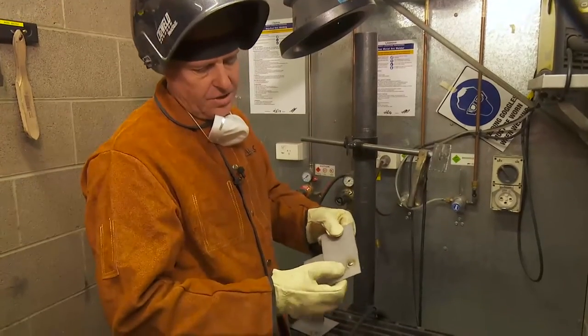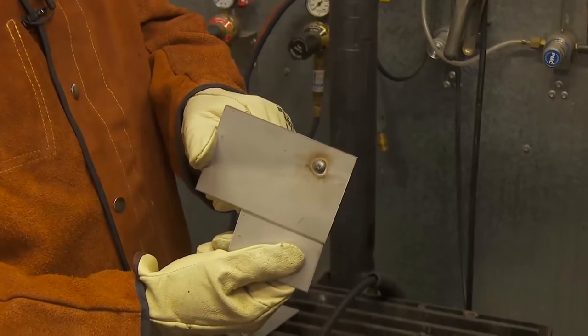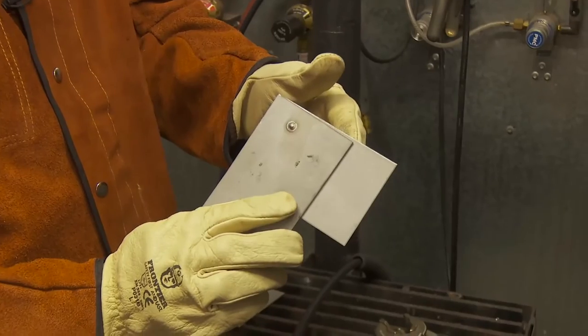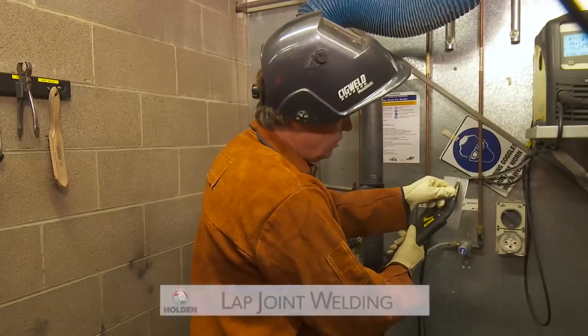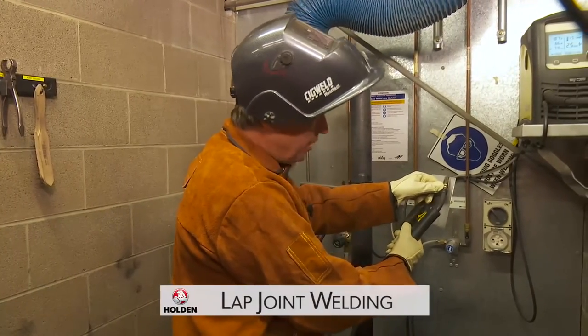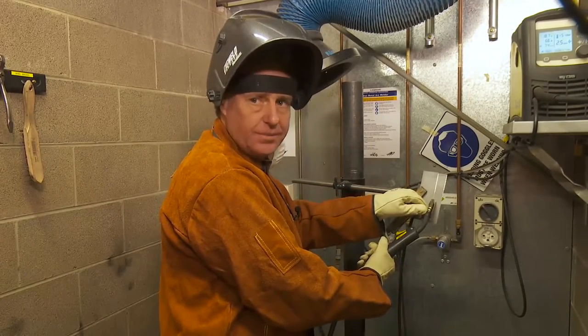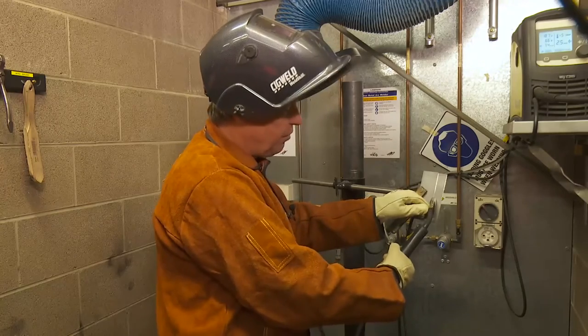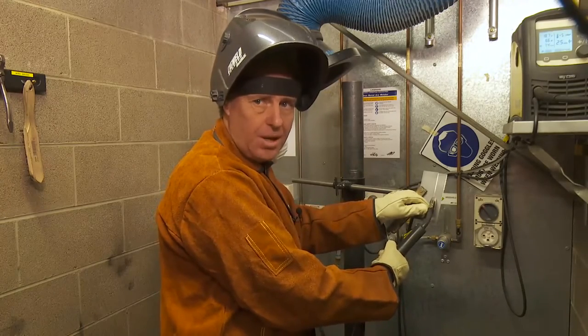So we have a good bead size, we have the sink in the middle that says it's shrunk, and we turn it over and we've got really good penetration. Our travel angle for this plate will be running down at about 45 degrees. Our work angle will be about 40 degrees into the joint. That'll place the weld bead on the seam.